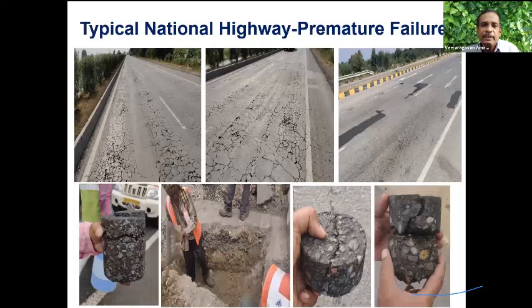This again is a highway. It's a shame to say that the highway failed, but this highway failed in 3 months. Whatever distance you're seeing failed in 3 months. Out of spending 2,400 crores, not 1 crore, 2,400 crores, it failed, it cracked. There are several reasons for that. I also investigated the failure. I gave a solution.